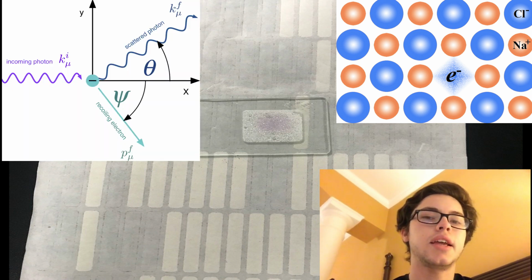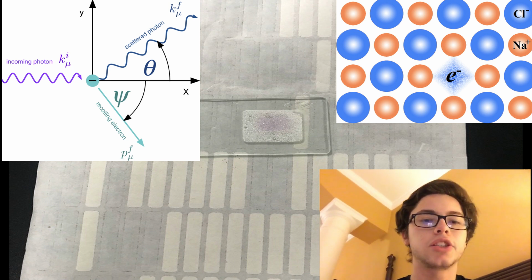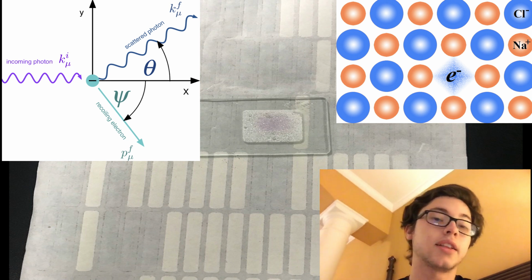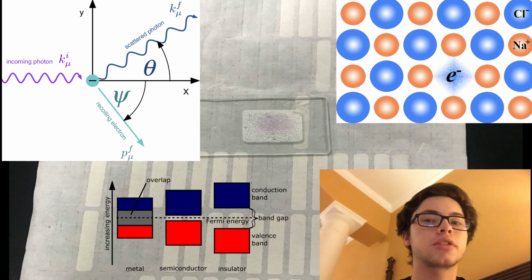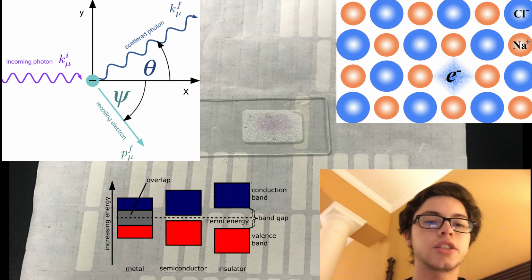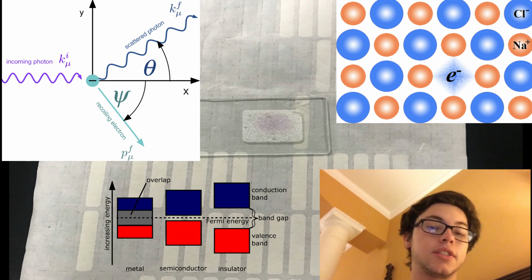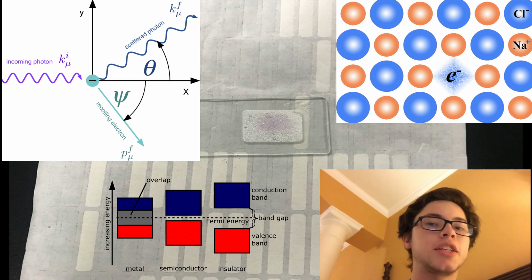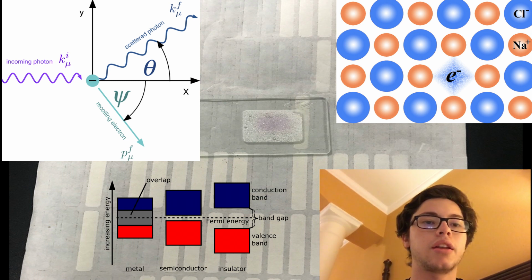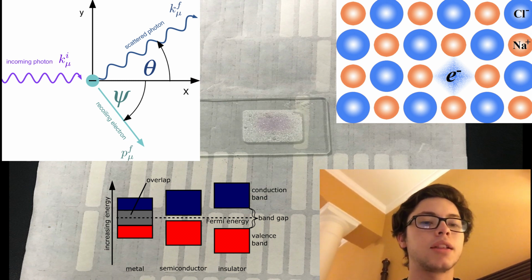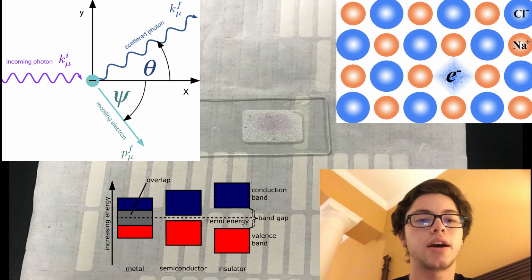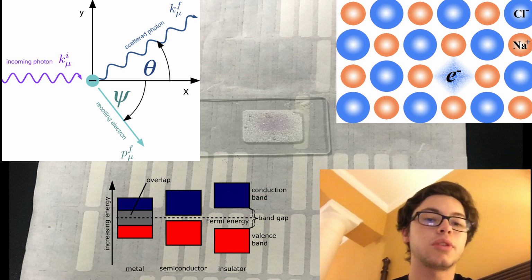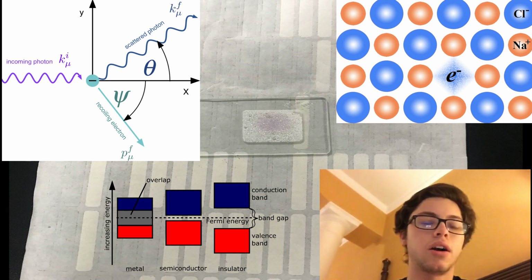In this case, the inelastic interactions of high energy photons with the electrons in the sample cause them to recoil, and for some semiconductors and insulators that have a large enough band gap, such as this salt, the electrons can be ejected and become trapped in the place of the anions. This results in a modification of the range of wavelengths the material usually absorbs, leading to a macroscopic color change of the sample.